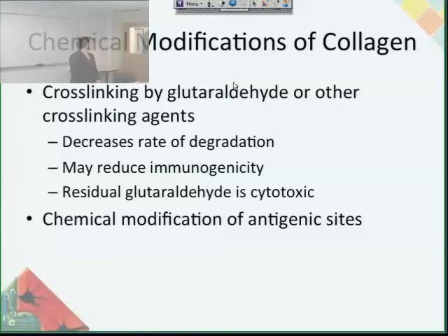And also there's some research that has shown that the inflammatory response to cross-linked materials is much, much worse than if you don't have cross-linking. And that's probably because it's less natural. You don't have that chemical cross-linking in the body, so you just sort of took away the whole reason why you use natural polymers, that they're biomimetic. But I think that depends on the degree of cross-linking, and it could be a really useful tool for modifying the properties of collagen sponges.